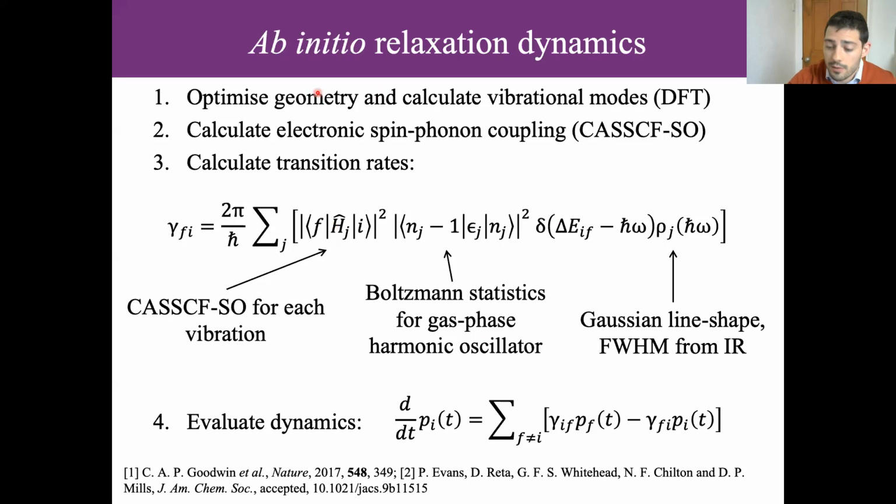For that paper, for this particular material, we decided to try an ab initio calculation of relaxation dynamics. So our approach was to use DFT to optimize the geometry of the molecule and determine the normal modes of vibration. Okay, so this is gas phase. We're ignoring the fact that this actually exists in the solid state with phonons and all kinds of things. So pure gas phase, very simple.